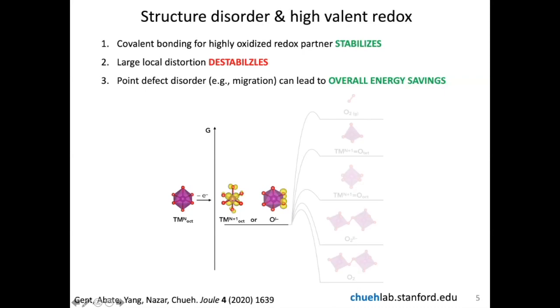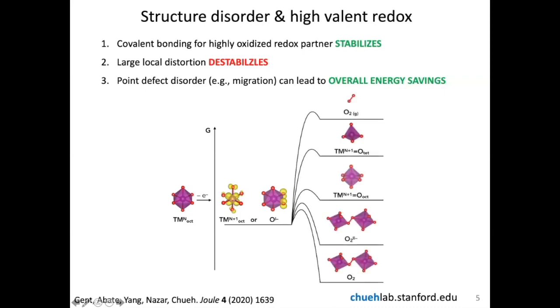On the right of the plot, you can see these various modes of accommodating for the local strain. You can, for example, form a higher order bond between the transition metal. You can migrate between octahedral and tetrahedral site. You can form a link between the oxygen atoms. In some cases, you can possibly even form molecular species in the material. And all of these will cause different contributions to the total energy of the system.